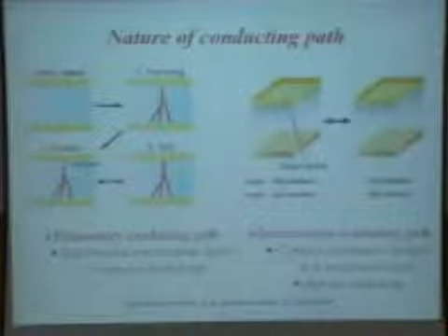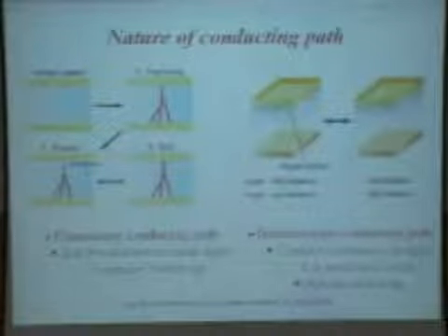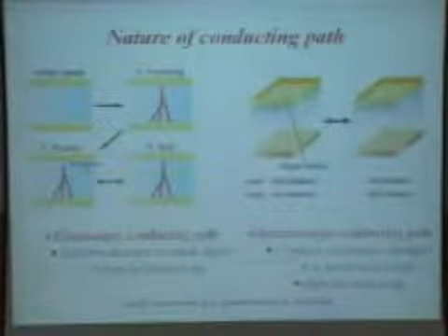This is the initial state. Nothing has happened. You make the device first. You are forming the device. What you are doing is applying a very high voltage. Some sort of soft breakdown of the dielectric material takes place, and you form a conducting filament. The dimensions of this filament are in the nanometer or micron range. What you have done is made some sort of electrical fuse at the nanoscale by applying this forming voltage, a very high initial voltage.